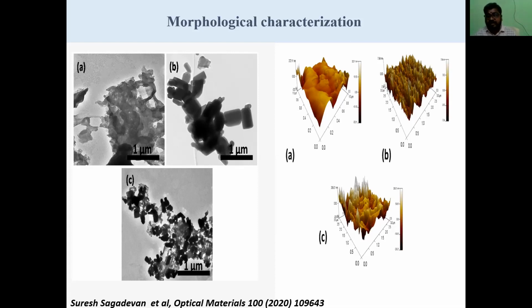And we also did the AFM analysis. You can see that figure A represents the surface morphology, the topographic image of the graphene sheet. This is graphene carbon nitride, which shows a sheet-like morphology. And B confirms a rod-like structure of zinc oxide. And figure C once again confirms the formation of the composite. You can see both are present, sheet and rod-like structures.